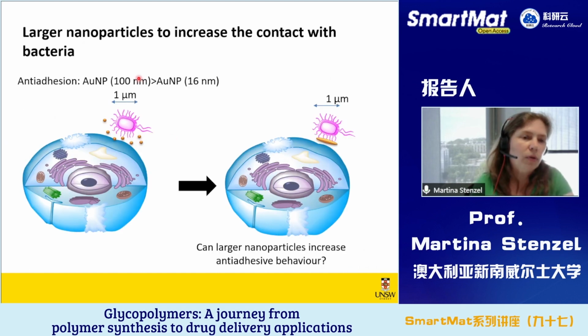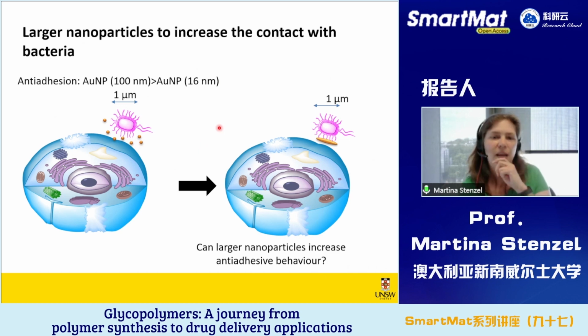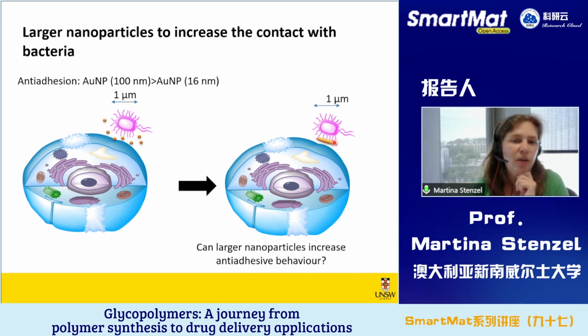So what we've done first is we worked with very small nanoparticles. We found first the 16 nanometer gold nanoparticles work quite well. But if we have 100 nanometer gold nanoparticles, it worked much better. And this is a comparison of sizes, where we looked at the bacteria around 1 micrometer in size, and we had 100 nanometer. So our hypothesis next was, if we have even larger nanoparticles like here with trehalose, it should work even better.